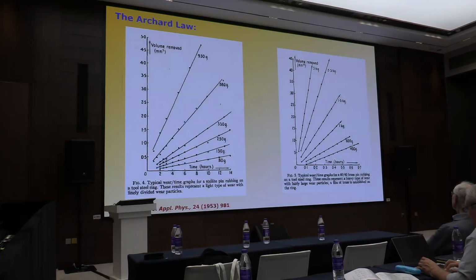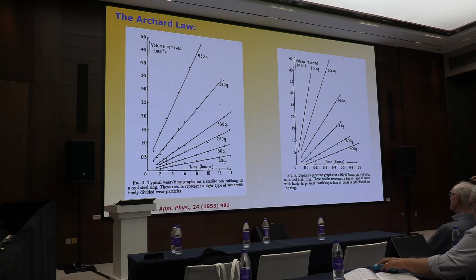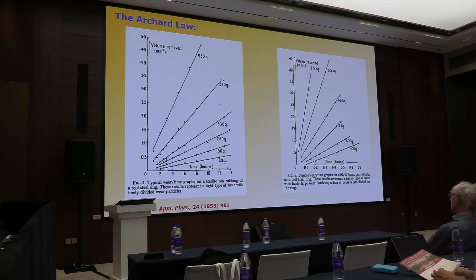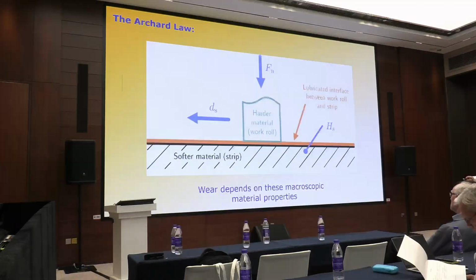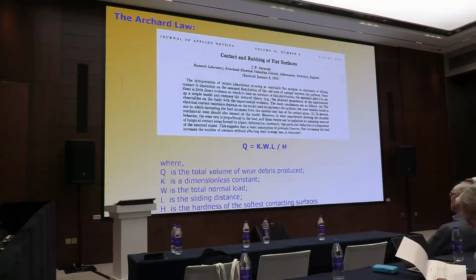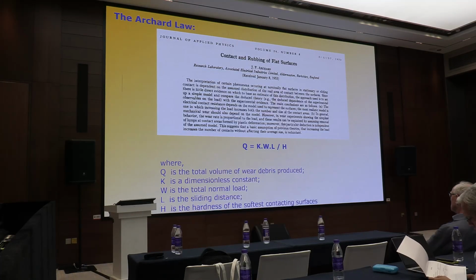Well, in this article, Archard proved that you have this linear relationship between, for example, the volume removed, the removal of the softer material, and different loads. When you increase the load, you increase the wear. It's in agreement with the equation published, or with this equation here. When you increase the load, you increase the wear. And when you increase the hardness, you decrease it.